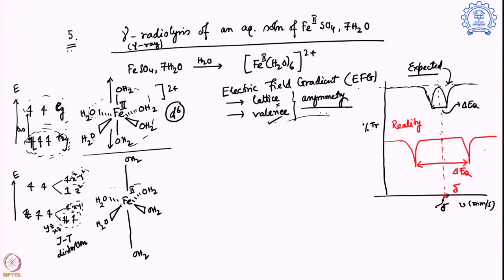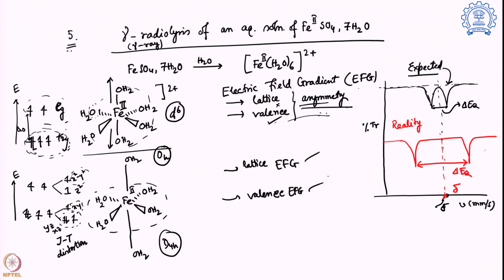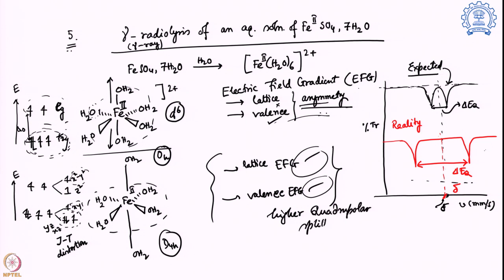And due to this interaction, now your lattice is also having an asymmetry, because from a perfect octahedral, it has now moved to a D4h symmetry. So, it will also trigger a lattice contribution for the electric field gradient, and the valence interaction is already there, and both of them will come into the picture, incorporating asymmetry around the metal. So, I am going to see a higher value of quadrupolar splitting, or delta EQ, and that is shown over here. So, that is what I am going to see if I dissolve iron sulfate in water, I am going to see this particular spectra.